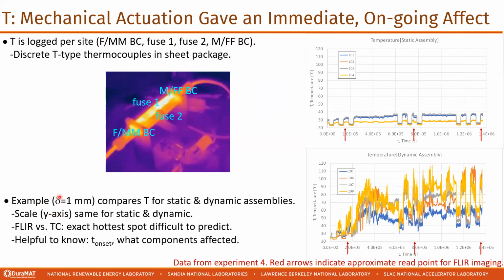And again, this is the example for later on. We were using a smaller deflection. This compares the temperature for the static and the dynamic assemblies. This time we have the same Y scale to give some sense of how much different the temperature is responding through the course of the experiment. And these temperatures are representative. If you go in and compare the FLIR results, like if you zoom in and look at the pixels, to the thermocouple, the exact hottest spot within the sample is difficult to predict, or it's difficult to get your thermocouple exactly there. But this certainly gives an order of magnitude sense of what's going on.